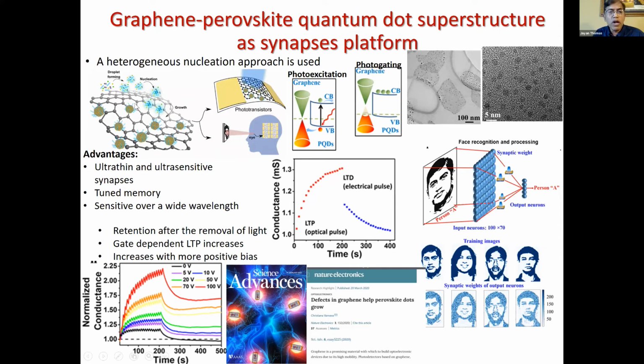So we followed a method. Here is the graphene, and we grow this type of quantum dots from the lattice of this graphene and convert it to a phototransistor type structure. The advantage is that the total thickness of the active layer is maybe less than 20 nanometers, extremely thin. Graphene by itself has very low light absorption capability, about 2.3% of visible light. But by adding quantum dots, its light absorption capability can be enhanced many times.